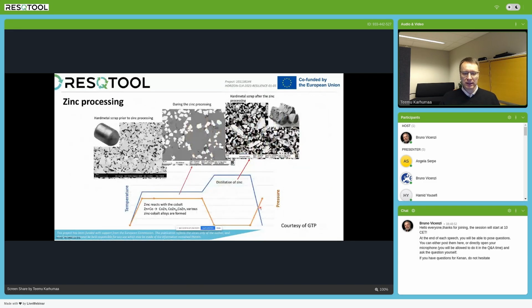Zinc processing is very simple. So we crush the hard metal parts to powder form with the help of zinc. So when hard metal parts containing tungsten carbide and cobalt are immersed into molten zinc, the zinc reacts with the cobalt binder. As you can see here on the left side, you see the typical microstructure of tungsten carbide and cobalt. When this part is put into contact with molten zinc, the zinc and cobalt alloy forms in between of the tungsten carbide grains, and this alloying distracts the tungsten carbide grains further from each other and creates space.